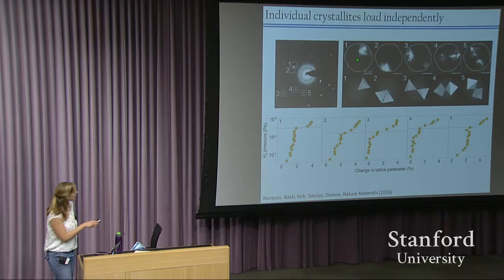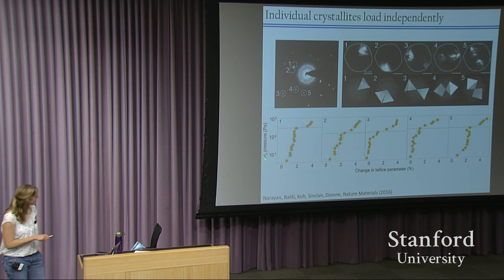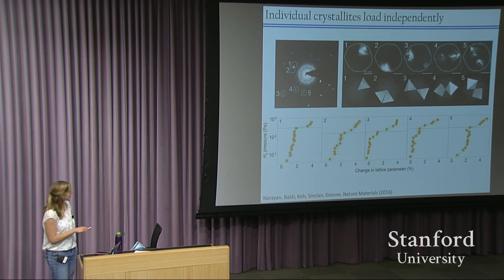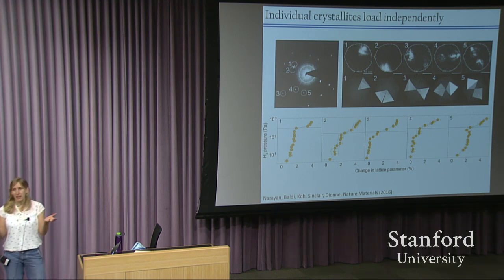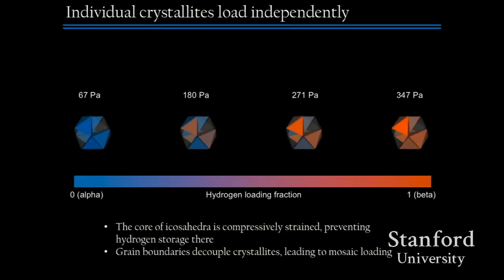And then what we can do is look at how individual tetrahedra or pairs of tetrahedra in the nanoparticle are transforming. So here are isotherms for, in this case, an individual tetrahedra. All the rest of these are pairs of tetrahedra. And you'll notice that the transition pressure from the alpha phase to the beta phase is occurring at different points within the nanoparticle. So this helps explain why there's a little bit more of a sloped transition. Basically, different parts of the nanoparticle are transforming at different hydrogen pressures. And we can take our diffraction data and our yields data and combine that together to make a video showing in three dimensions how these polycrystalline nanoparticles are transforming.